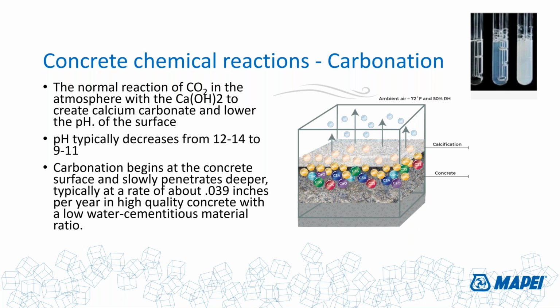I will unfortunately tell you this is a slow process, and it will take some time. As you see here on the left side of the screen, that rate is about 0.039 inches per year in high quality concrete with a low water cement ratio. That number may change. If you've got a higher water to cement ratio, there's more calcium hydroxide on the surface and so on. But this is something that takes time, and it's why we would highly recommend you wait a little bit of time before you get on the concrete with water-based adhesives, and not just say, okay, it's been down there for 5 days, let's put a PSA adhesive, install LVT on it. It's not necessarily a great idea.